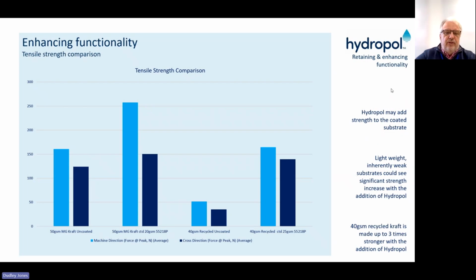If we look at the functionality of the product, here we're looking at tensile strength. You've got 4 bars. Here you have a 50 GSM kraft uncoated, 50 GSM kraft coated with 20 GSM of Hydropol. And here you have a 40 GSM recycled, 25 GSM coated of Hydropol. The light blue is machine direction and dark blue is the cross machine direction. So you can see in both instances, we see Hydropol adding strength to the paper. In a way, lightweight, inherently weak substrates could see significant strength increase with the addition of Hydropol. But also, if you're thinking about down gauging, Hydropol will add strength.